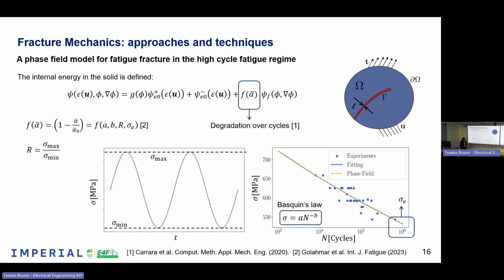A and B, they are the coefficients of the Basquin's law. This Basquin law is the equation that is defining the SN curve for fatigue that we were talking before. This curve that was relating the load with respect to the number of cycle to failures. Then R is the stress ratio. It's just the quotient between the maximum stress in the cycle and the minimum stress in the cycle. And finally, sigma E is what they call the endurance limit. It means the fatigue strength, the fatigue load, for which we will arrive to 1 million cycles. This parameter is really important, and please take it in mind because we will use it later.